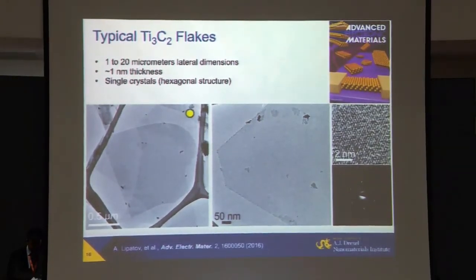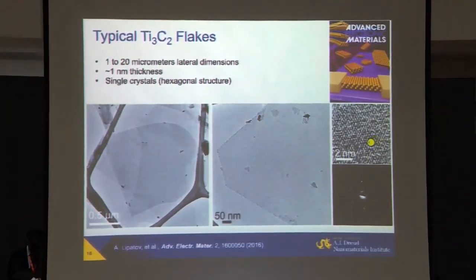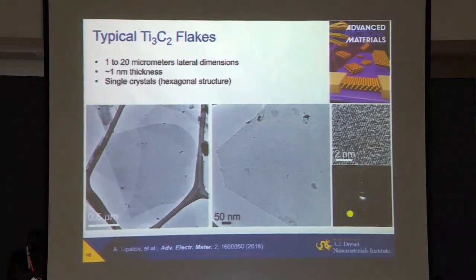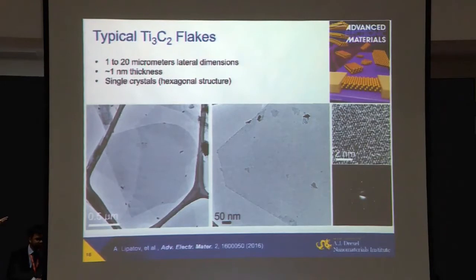Here a couple of layers are overlapping, and if you magnify it further, you will see that each of them has an ordered lattice, and they're single crystals, and this diffraction pattern shows. So we have flakes, which are freestanding.